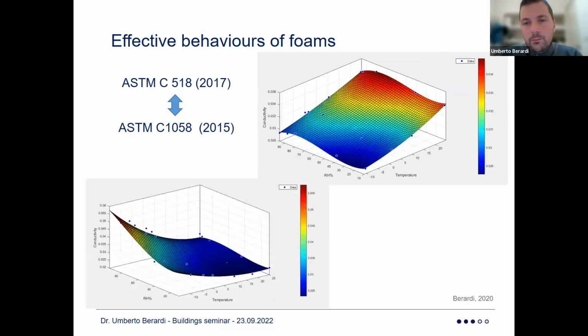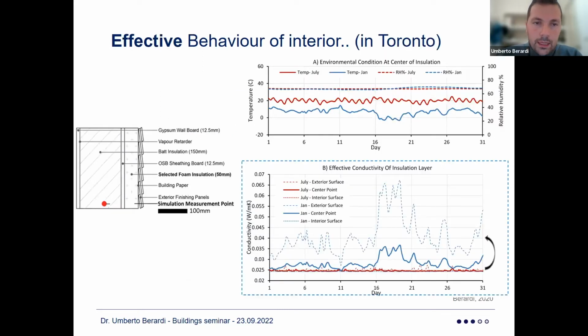And we've been doing this kind of modeling and studies where we've been looking at real field materials, putting sensors, thermocouples and thermal heat flux meters, and looking at how in winter, for example, you get very stable conditions, and then on the other side you start getting significant challenges when you get lower temperature. You can see here the dotted line that represents the general result of the exterior surface of that same material, supposed to act at 0.02 watt per meter Kelvin, ended up being at 0.06 watt per meter Kelvin.